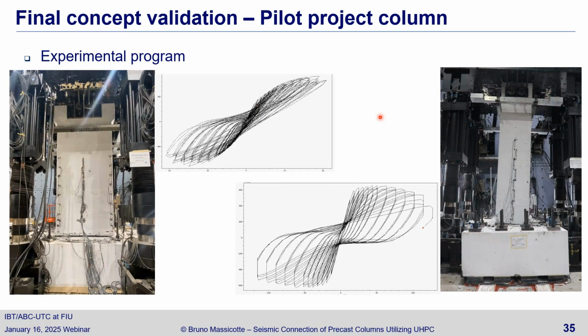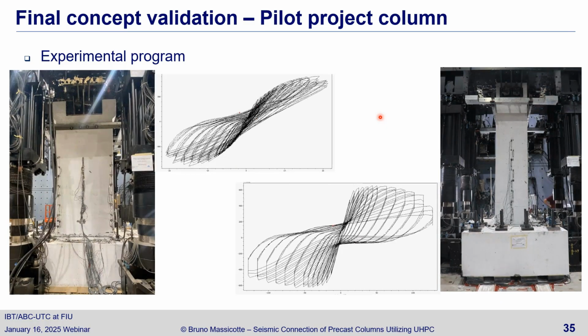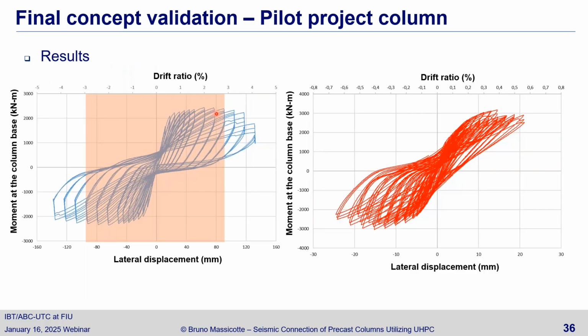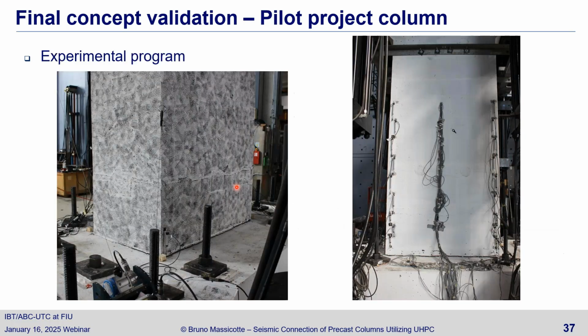So the behavior was quite good in terms of drift ratio, and the behavior we got in the longitudinal direction under the weak axis direction, a very ductile column. And at the end, it's what you see, although we pushed the column quite far, there was no damage that could be observed outside the column. So it was in pretty good condition. And at the design displacement, there was no visible damage to the column.